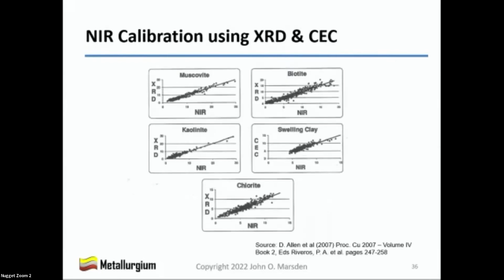You can see here, this is her calibration she showed him over Zoom, where she showed how muscovite, biotite, kaolinite, swelling clay, and chlorite were calibrated using XRD results. The one on the right there, which is swelling clay, is calibrated using cation exchange capacity. So you can calibrate the swelling clay to be read on the near-infrared instrument. She went on. Actually, once you've done the calibration, it's very cheap to run NIR analyses at the mine site. Costs us less than $5 a sample.